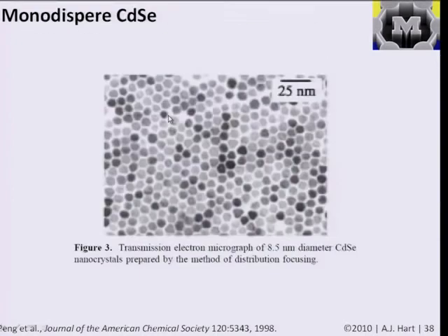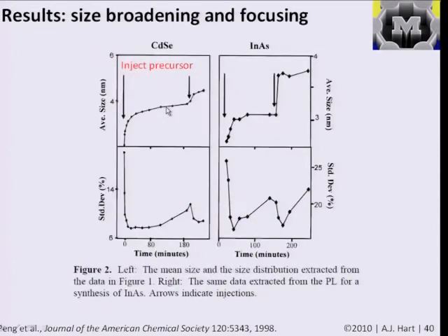And it turns out that what we saw in the TEM is in fact a fantastic result, a very highly monodisperse distribution of structures which gives those very pure optical properties. And ideally, we might want to have them atomically precise, but getting down to the levels of standard deviation being a few percent of the diameter is a very good result that is enabled by understanding of these nucleation and growth dynamics. So that's where we will pick up next time.